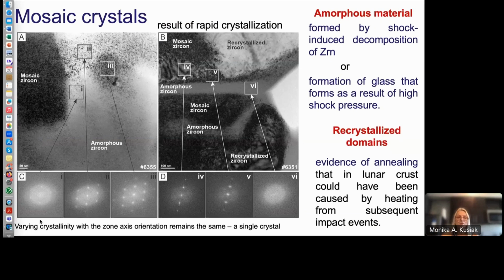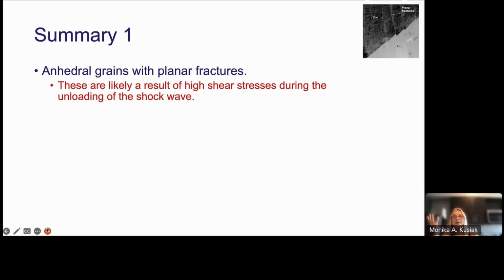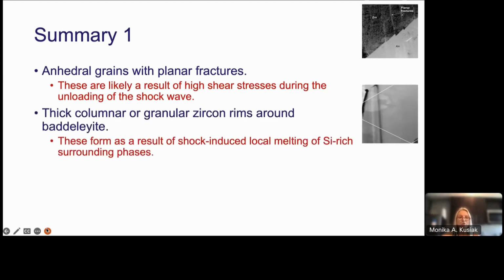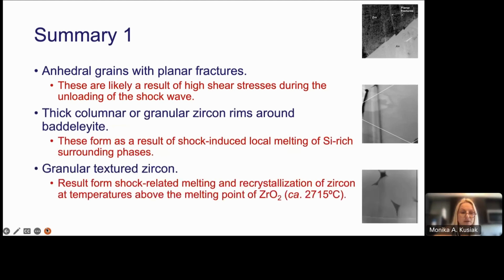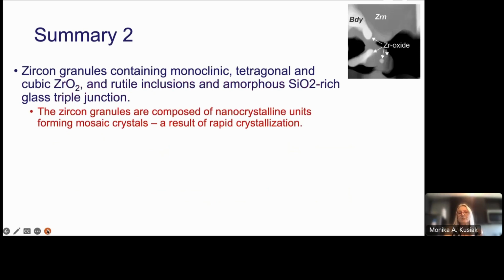So now I'd like just to summarize our observations. We had anhedral grains with planar fractures, which are likely the result of high shear stresses during unloading of shock waves. We had thick columnar or granular zircon rims around baddeleyite, and again it was shock-induced local melting of the silica-rich surrounding phase. Granular textured zircon results from shock-related melting and recrystallization of zircon at temperatures above the melting point of zirconium oxide, 2715 degrees Celsius. So this is the temperature of cubic zirconium oxide. And as well, these granules contain monoclinic, tetragonal, and cubic ZrO2, as well as rutile inclusions. So this is an effect of rapid crystallization.